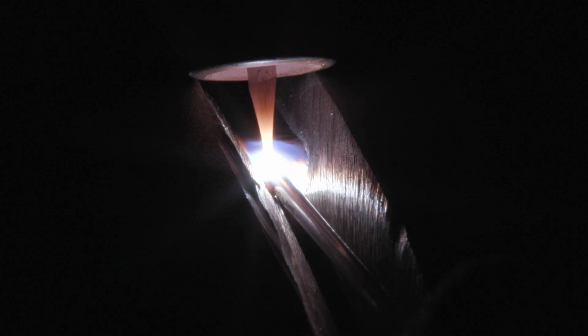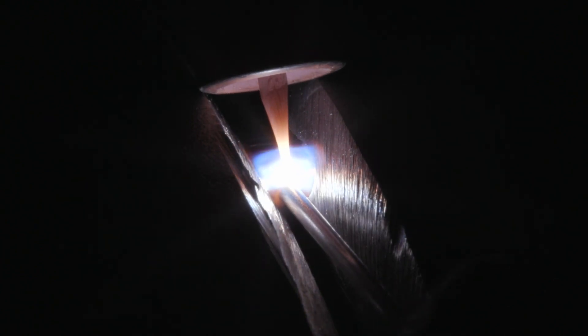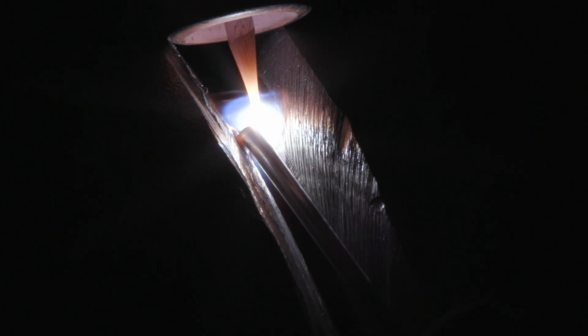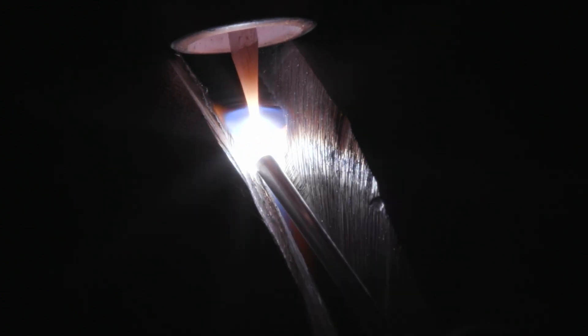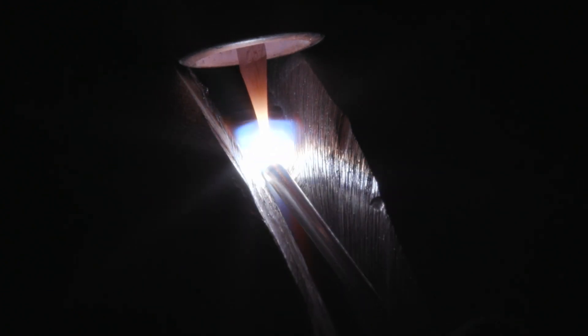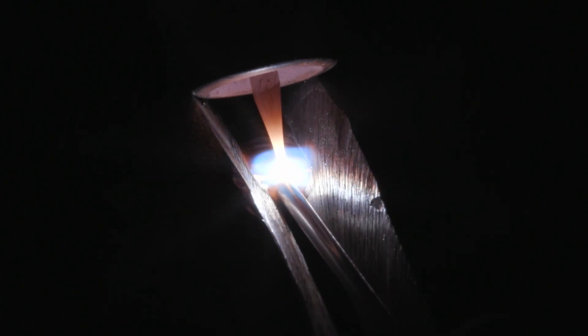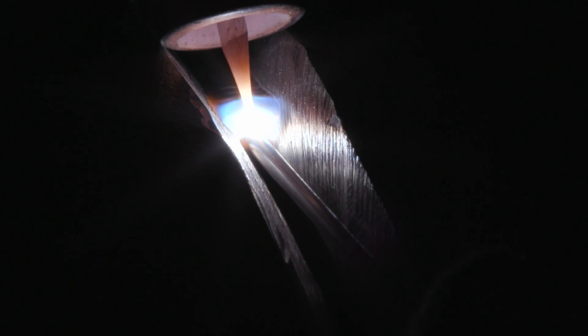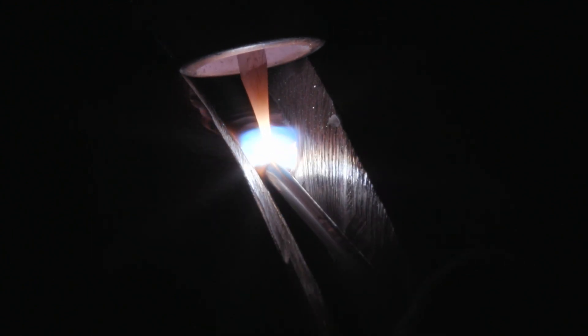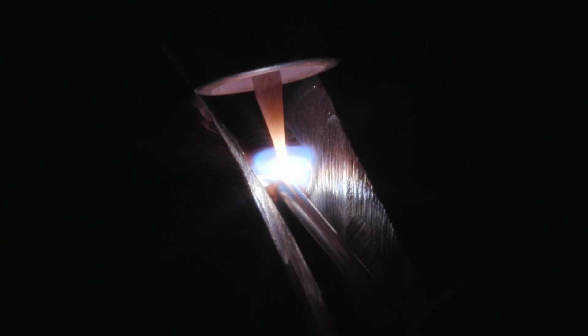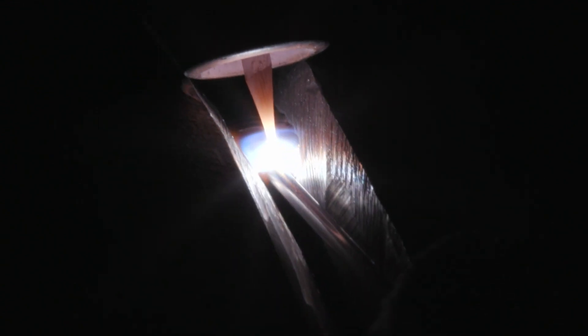So if you notice what I'm doing, I have about 100 amps on the machine. I'm dabbing into the hottest point on the pipe. So the gap is not very wide. I'm just using very minimal movements, just kind of dabbing into the hottest point which is in the middle. Now there's other areas that you can dab. If I dab on the very leading edge, I don't get the full amount of metal that's going into the root pass. And I might get a really flush or even a root pass that kind of slightly undercuts.